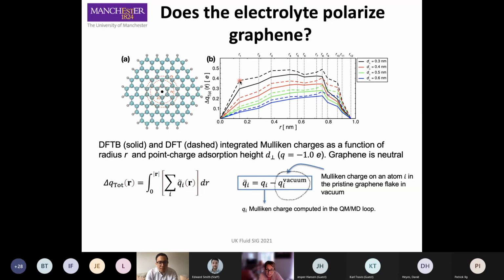Basically the plot starts here. The various colors correspond to the distance of the ions from the flake of graphene. You can see that as the ion gets closer, the curves from blue, green, red, and the black curve correspond to the ion approaching the surface. The amount of charge that is delocalized, that is created by the presence of the ion, increases. And as I was mentioning before, this polarization is very large in size, because the effect of the ion is felt up to here.